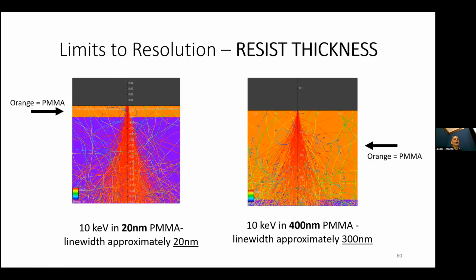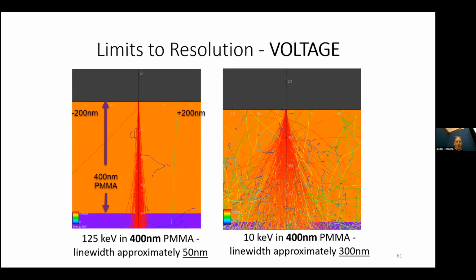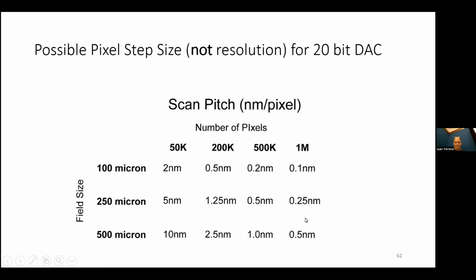And typically, if you're using a reasonable resist range, it's like less than, I don't know, 400 nanometers or something. Even at 50 kV, your forward scatter is going to be minimal for most patterns. So if we're at 125 kV, even in 400 nanometers of PMMA, we still get a 50 nanometer spot. But if we tried to do that same thing at 10 kV, we're going to get this 400 nanometer spot.